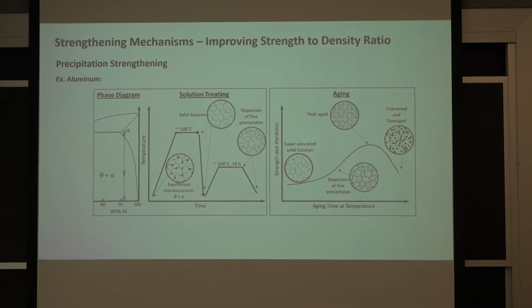That's a big problem. At that point, it's very possible for these dislocations to actually work their way around these particles and not have to cut them at all. And actually, the strength of the material begins to drop off, and you get a material that's less strong.